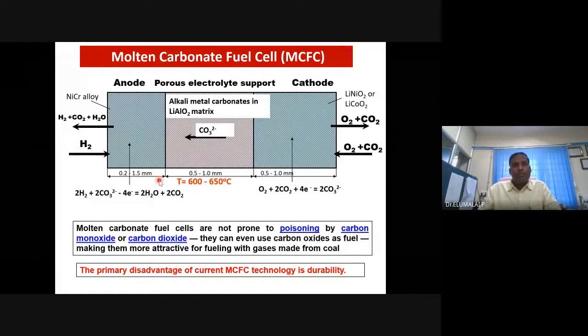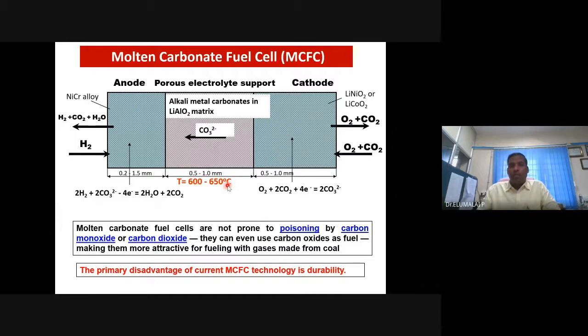Okay. So nickel chrome as an anode, lithium nickel oxide or lithium cobalt oxide as a cathode, and the electrolyte is alkali metal carbonate, lithium carbonate, sodium carbonate or potassium carbonate immersed or dispersed on lithium aluminum oxide. It is operated at 600 to 650 degrees, and you can even use carbon monoxide as a fuel. Carbon monoxide itself as a fuel.